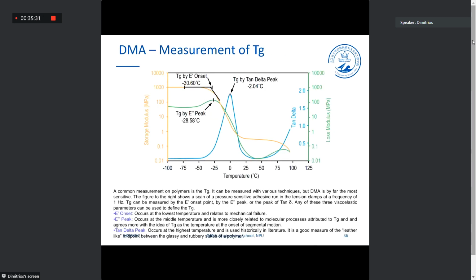omega. Now, I use this slide to show you that some people use DMA to measure the glass transition, but sometimes they use different parameters of the DMA measurement, which are wrong, in order to obtain the glass transition. What we have said already is that the glass transition is given by the peak of the tan delta over temperature, or approximately the middle of this significant downshift when the material softens completely. So some people also claim that the Tg can be obtained by the onset of this significant downshift, which is wrong.